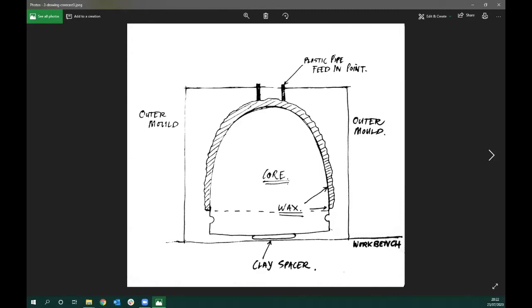So this whole mold will be turned upside down and placed in a steamer. In the trade, it's called an autoclave, and I like to use a commercial Baby Burco boiler with a little trivet standing in the bottom, turn it upside down, and in about half an hour, once that water has reached a rolling boil, all the wax will be removed from that little cavity there, leaving a hollow space into which the glass can flow.